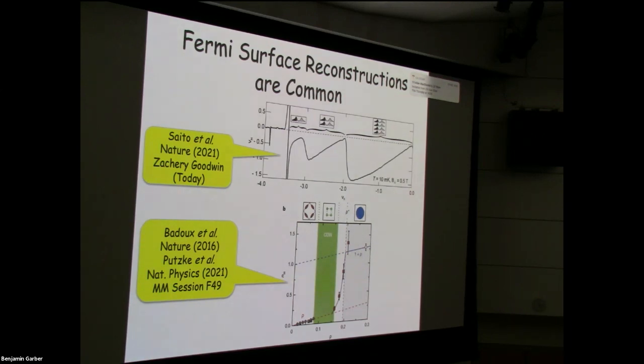all over the phase diagram of magic angle twisted bilayer graphene is that you get a kind of ferromagnetism. You get broken symmetries of the spin and valley degrees of freedom without, in most cases it seems, breaking translational symmetry. So I call that a generalized form of ferromagnetism. One of the types of observations that sees it most obviously is this measurement of Hall density. This is electron density, size of the Fermi surface, measured by measuring the Hall effect.